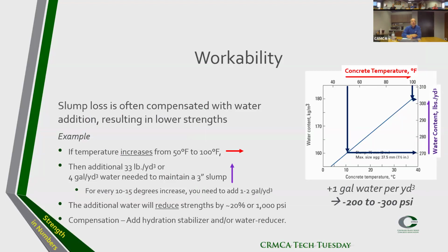Let's talk about workability, slump loss. Slump loss is often compensated with water addition, resulting in lower strength. So here's an example. I'll go through that chart. What we see up there is if we take a temperature of around 50 Fahrenheit, we go down the graph, we see that we need, in this example, around 270 pounds of water per yard of concrete. If we go from 50 to 100 degrees, given this is an extreme example, we now need an additional 33 pounds of water. That is about 4 gallons per yard additional to maintain the same slump.